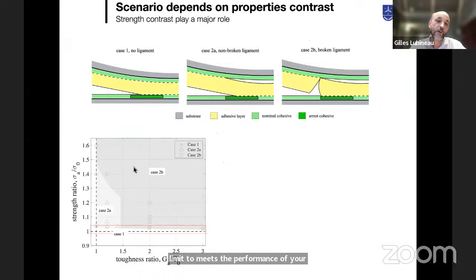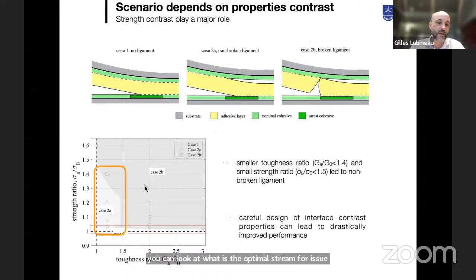So what you can do when you understand this is that you can start to optimize your surface treatment, and you can look at what is the optimal strength ratio and the optimal toughness ratio between the dark green and the light green. So you optimize this mechanism. So you promote the mechanism with ligaments, the one that is here, and you make sure that you always get this one.